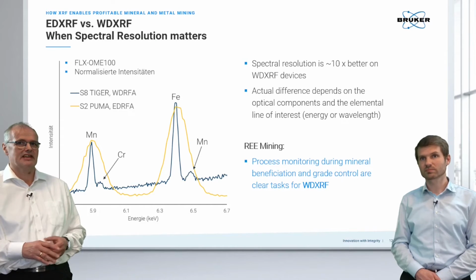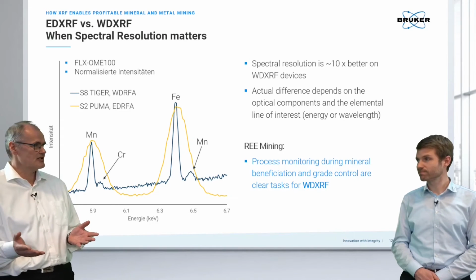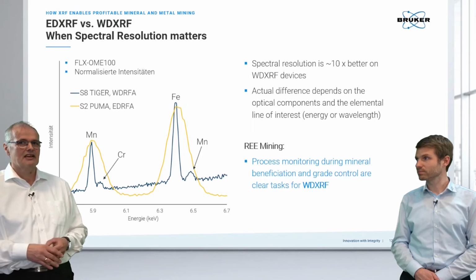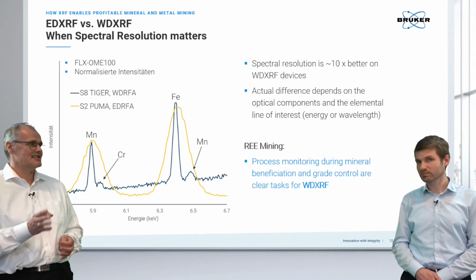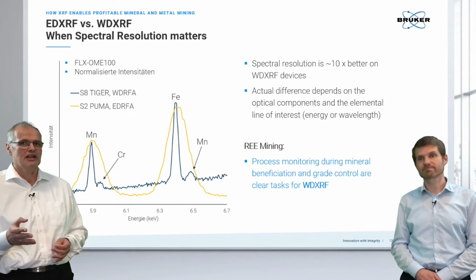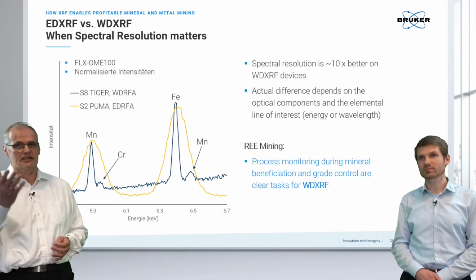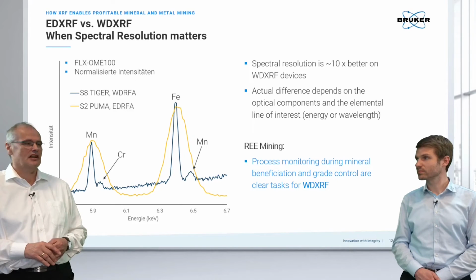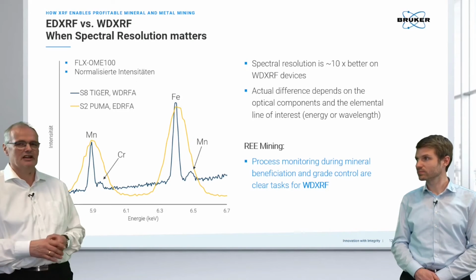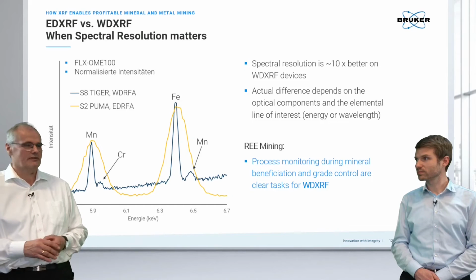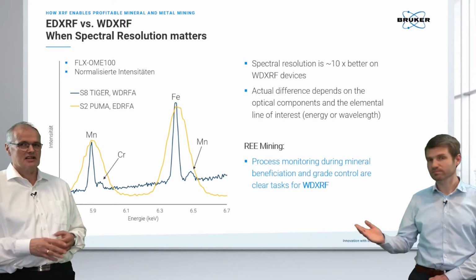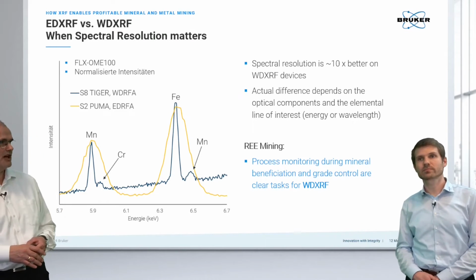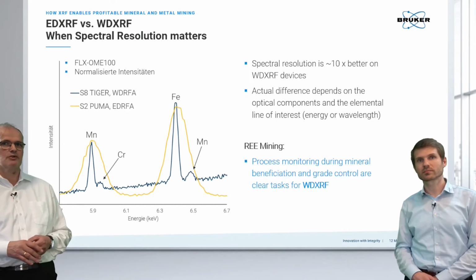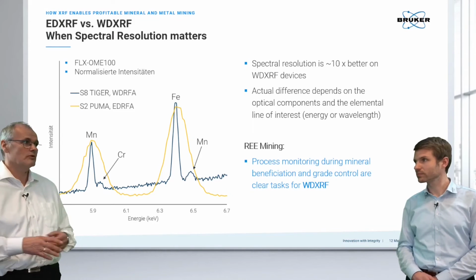The one is basically analyzing simultaneously the range of elements. The other one can be optimized element by element and therefore is giving us the right answer. Here we see that iron and manganese is covered under the one peak in ED, but separated in wavelength dispersive. And this gives us some indication that those applications might be better to be done with wavelength dispersive. Others are okay with energy dispersive.